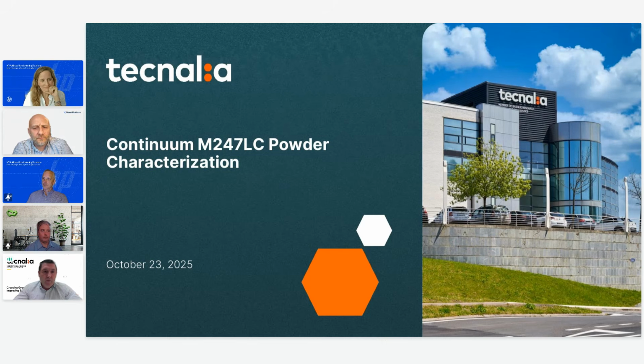So if we want to have a powder that is adequate for the binder jetting process, we need to bear different aspects in mind. The first one, of course, we need to make a proper chemistry analysis of the powder, just to make sure that we have the nominal composition we are supposed to have, to avoid further problems, which in this particular powder are very important. For instance, the carbon and oxygen levels. Then we also need to have a look into the physical properties of the powder, meaning the particle size distribution, and then all different physical properties of the powder.